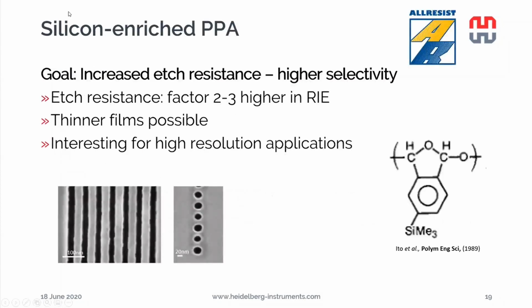So let's have a closer look. To increase the etch resistance, we have chosen a silicon-enriched PPA with one of our partners from Allresist, and actually found out that the etch resistance is about 2 to 3 times higher in the reactive ion etching. Therefore, we can use thinner films, and with thinner films, we can get higher resolution pattern transfers, as you see in some examples of the current testing that we're doing. The silicon-enriched PPA has a small side chain of a silyl side group on this PPA.